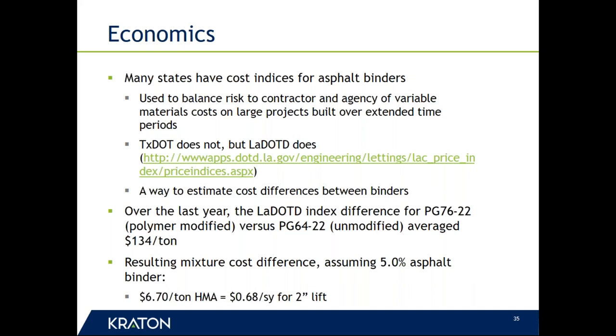If you assume 5% asphalt binder, that means about 68 cents per square yard for a 2-inch material. And when you put that in perspective, looking at the performance benefits that we talked about, and you start thinking about the overall cost of the project in terms of pavement markings, traffic control, large projects, if you have bridges, earthwork, that sort of thing, this is practically invisible. And yet what you're able to buy with this is something substantial if you're able to cut down the amount of time you have to take to go out there and repair, or reduce the number of activities you have. And that is fundamentally why you've seen the increase in the use of polymer modified asphalts in recent years in the U.S.